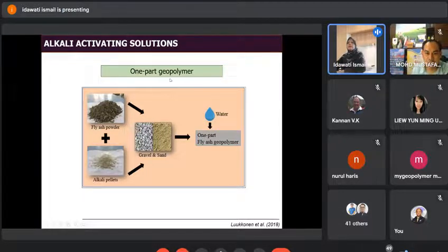There's another type of mixing that we want to look at, which is one part geopolymer binder, one part geopolymer concrete, whereby you don't use solution. Instead, you use alkali pellets. For example, if this is sodium hydroxide, you just mix it with your fly ash.